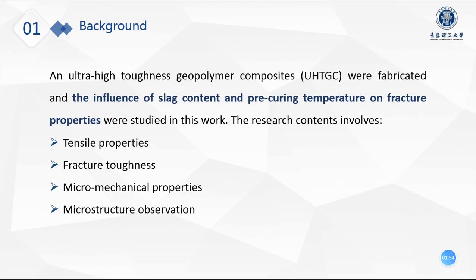In this work, ultra-high toughness geopolymer composites were fabricated, and the influence of slag content and pre-curing temperature on fracture properties was studied. The research contents involve tensile properties, fracture toughness, micromechanical properties, and microstructure observation.